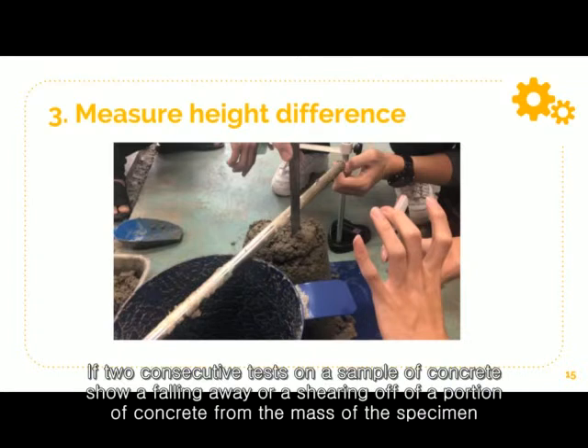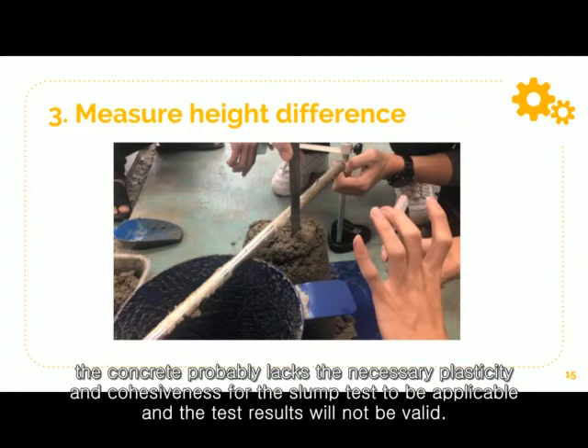If 2 consecutive tests on a sample of concrete show a falling away or a shearing off of a portion of concrete from the mass of the specimen, the concrete probably lacks the necessary plasticity and cohesiveness for the slump test to be applicable, and the test result will not be valid. Now, let's see the outcome of the experiment.